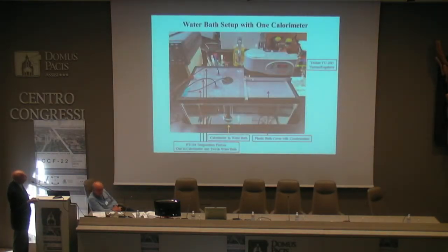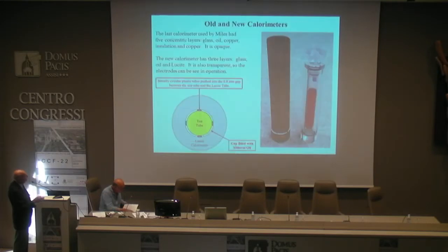So this is a photograph of the setup from a few weeks ago when we only had one calorimeter in place. The calorimeter is shown here. These are the temperature measurement probes, the thermal controller here. It's been very, very useful to put this plastic cover over, both to reduce evaporation and also to improve the temperature stability. We could insulate it if we have to.